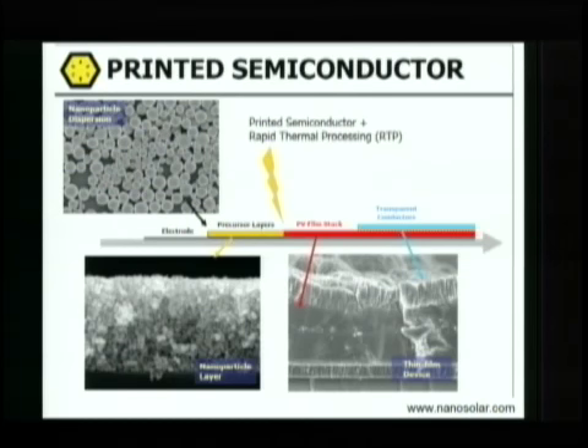There's a startup company nearby called NanoSolar, and they have come up with a way to print another thin film semiconductor called CIGS, which stands for copper, indium, gallium selenide. And I can't tell you exactly what's in those particles, but it contains those elements. And they print that down in a roll-to-roll coating machine. It's not completely unlike a newspaper printing press. And they print those particles down, and then they heat them at about 400 to 500 degrees, and those particles fuse together, and they end up with a high-quality thin film of the semiconductor, and they are able to make solar cells with 17% efficiency.